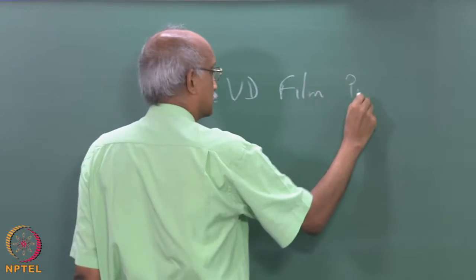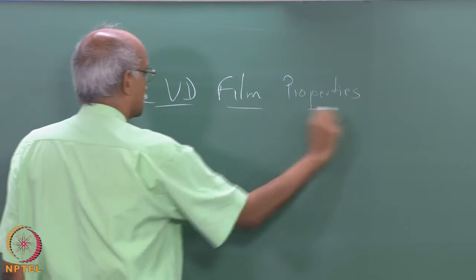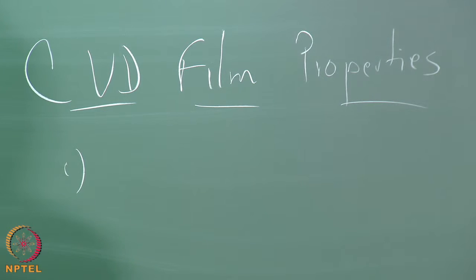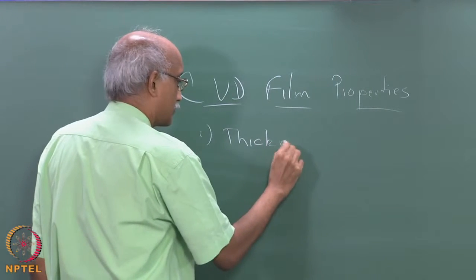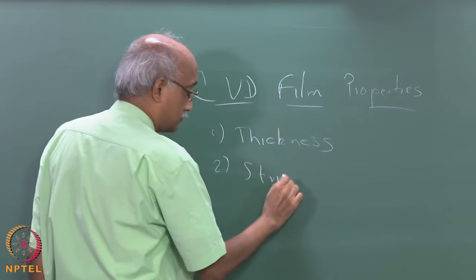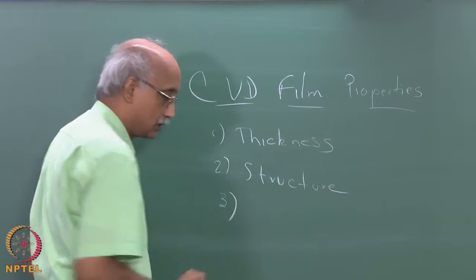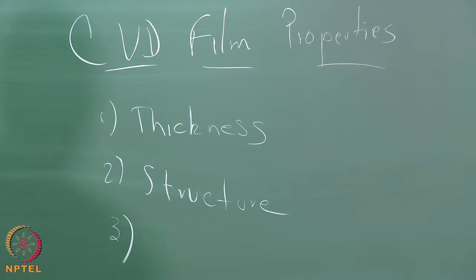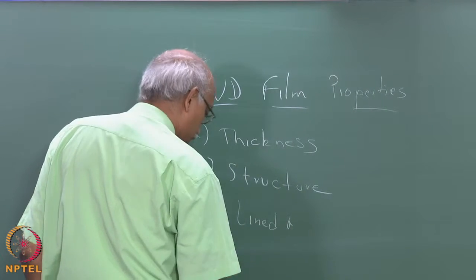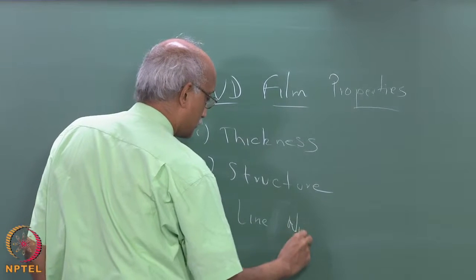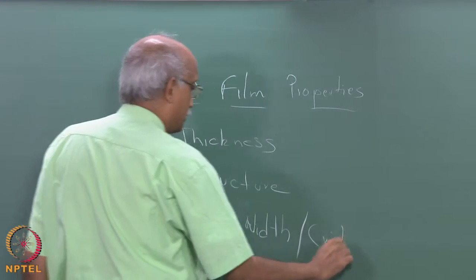So when we look at a CVD film, the things that obviously pop out in terms of important parameters to measure, indirect parameters, right? Not the functional parameters, but the indirect measurements. The key ones would be, I would say the number one property that you would try to measure is thickness. And structure. The third one is what's known as line width. Also, critical dimensions.